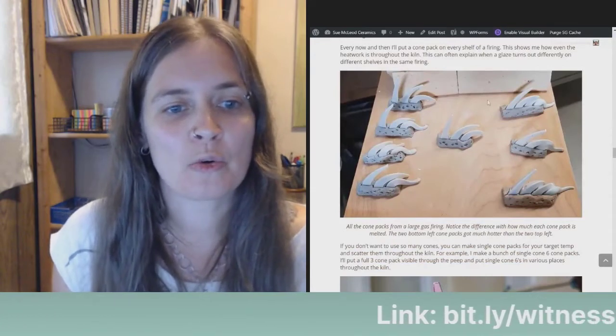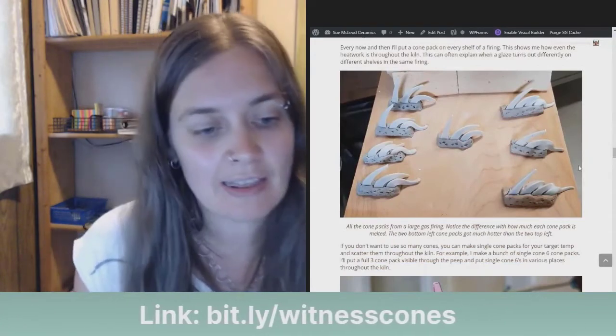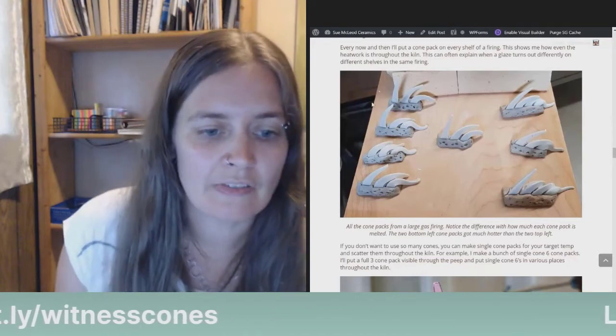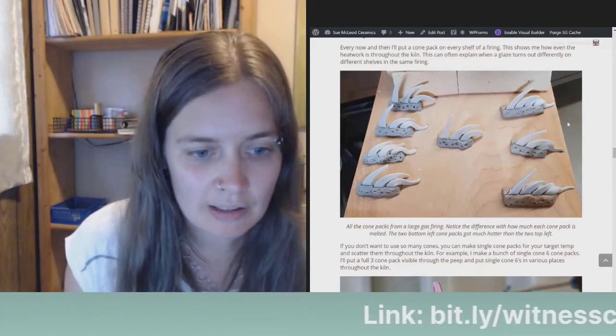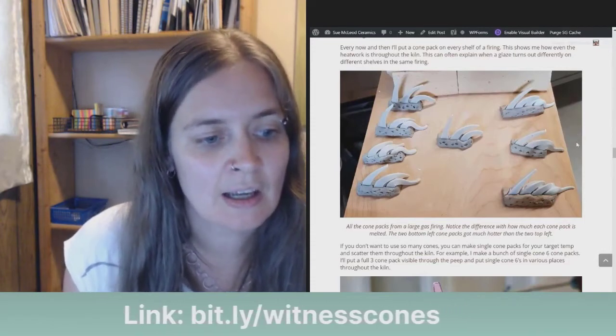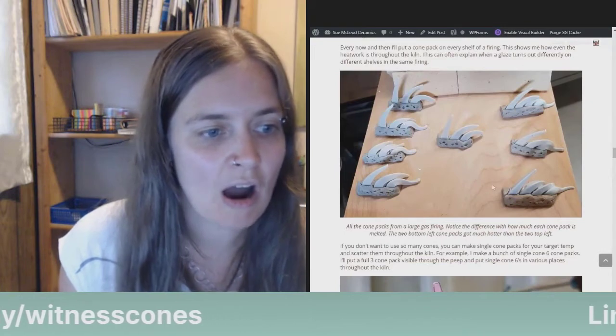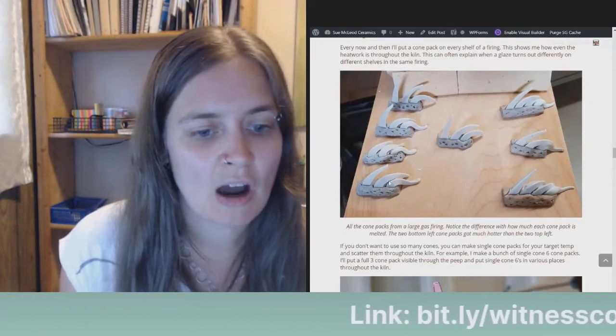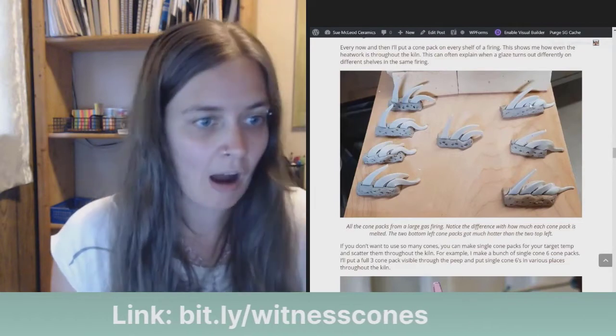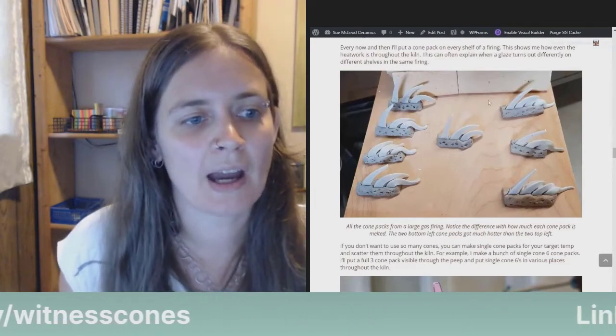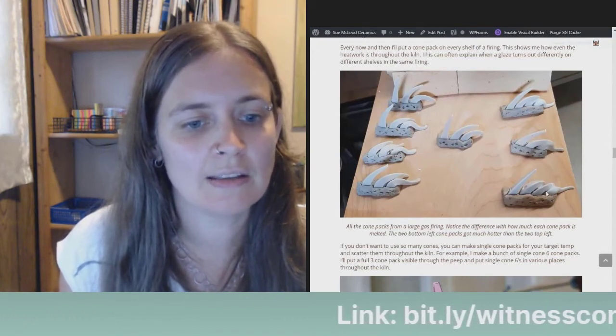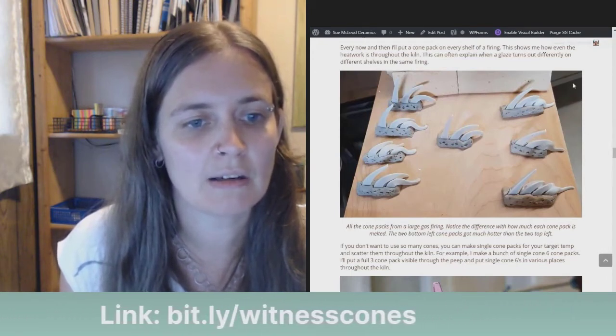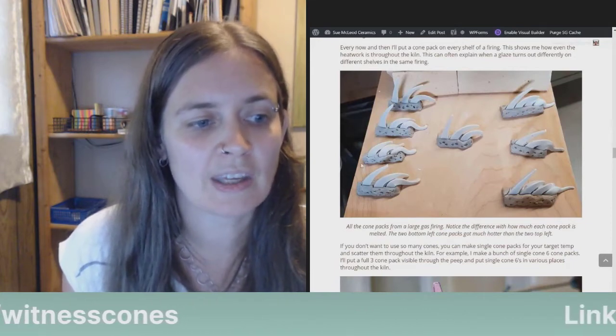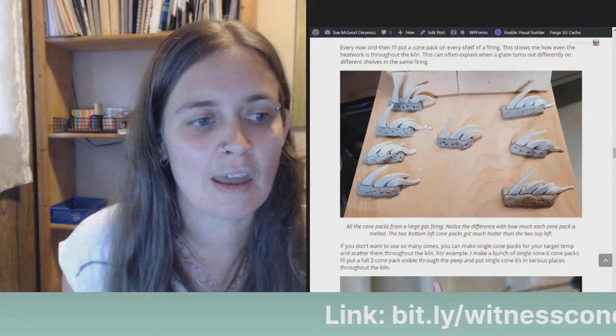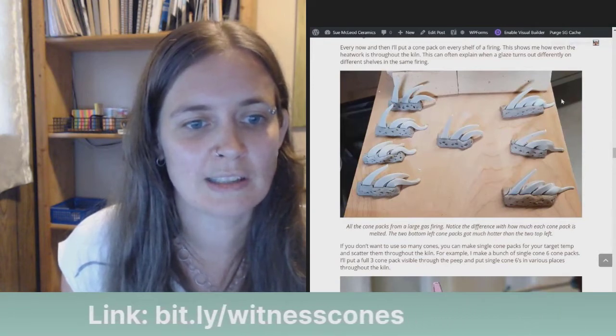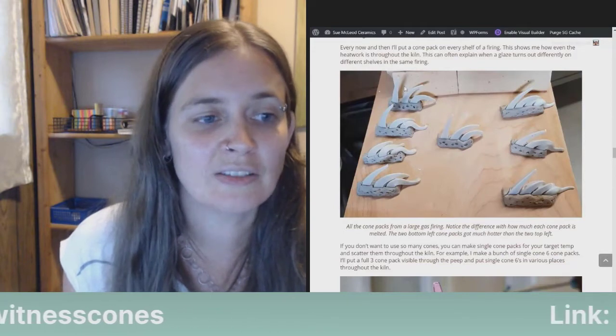So these are all the cone packs from a large gas firing that we did. And so you can notice the difference with how much each cone pack is melted. The two bottom left cone packs got much hotter than the top two on the left. These are set up kind of the way they were configured in the kiln. So these were on the bottom shelves and then the middle and then the top shelves. So you can see that the bottom of the kiln got significantly hotter than the top of the kiln. And then also the right side of the top got hotter than the left side of the top.